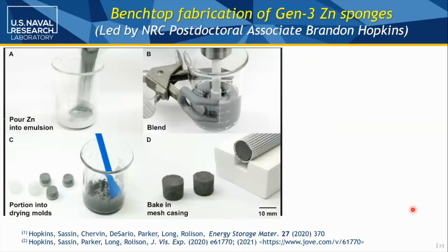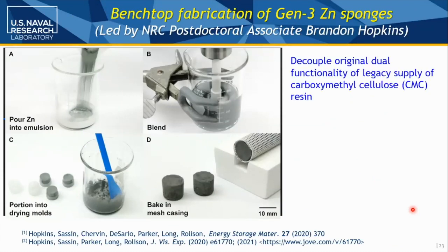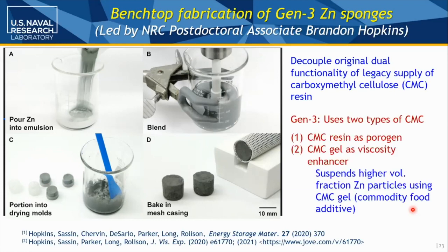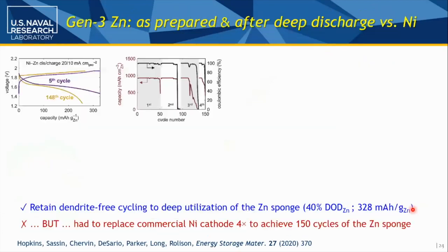New postdoc, new protocol. Brandon recognized that our legacy carboxymethyl cellulose that we used to make the emulsion to make the zinc wasn't working when you upped the amount of zinc in the system. So he split the functionality. He worked with resin as a porogen, and he worked with the food additive carboxymethyl cellulose powder, not a resin, to increase the viscosity. And that let him get the amount of zinc up even higher than Jesse was able to work with, the 2.1 grams per cc. So now we're at 2.8 grams per cc.